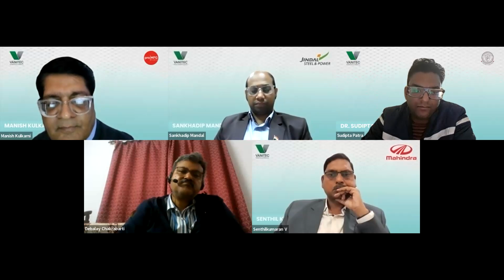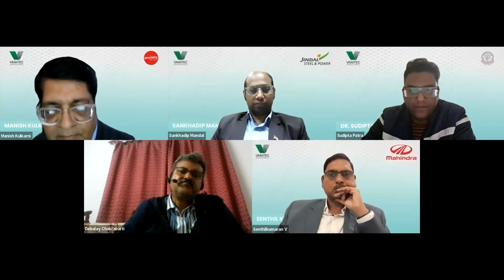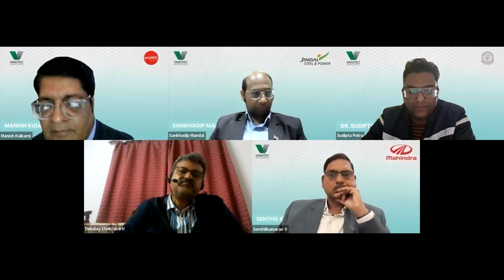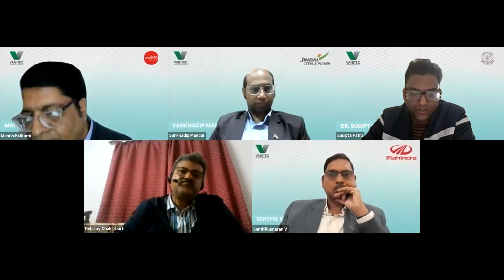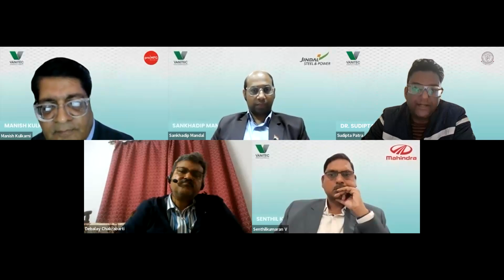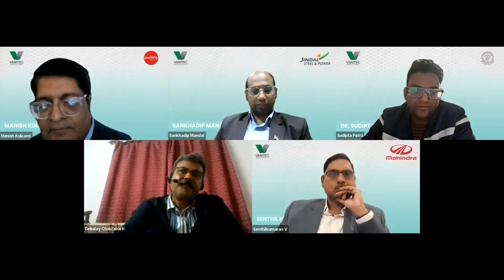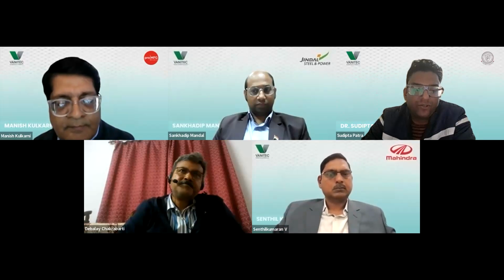Probably 0.5% grinding may be okay, because we have experienced that with vanadium these surface defects do not come in the cast slab. The titanium oxide and titanium nitride normally cause the surface defect. And if you can control the oscillation frequency of mold oscillation and the negative strip time properly, then if you can avoid these oscillation marks, you can go for even 0% grinding loss. So that is my answer, that vanadium addition is very helpful in this point for the stabilization.